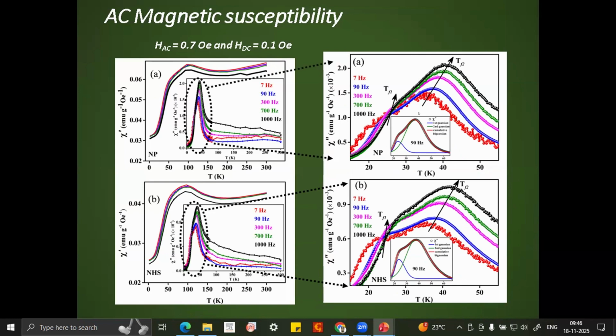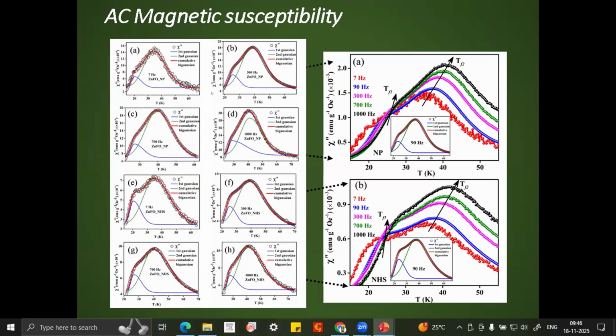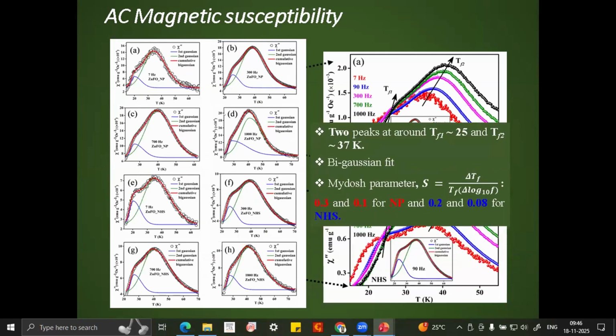Now with this, we can see that there is a shift in the peak temperature with the frequency of the AC magnetic field. Now this is a signature, a fingerprint of spin glass nature, or let's say the superparamagnetic nature. To identify exactly the peak position, we have fitted each plot with bi-Gaussian fits. With the fits, we have identified the peak positions.